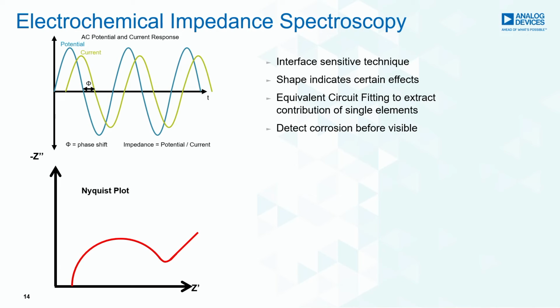This way you can, for example, detect corrosion before it's even visible, check if your coating is working, for example, is it taking up water? Or you can make label-free immunosensors. Label-free means often, for example, if you look for a certain DNA, you have to attach another molecule that will give a nice electrochemical signal. With impedance spectroscopy, the change of the interface due to interaction of certain molecules can be large enough to have a good signal without introducing any labels. All right, there is a bit of a disadvantage. It's a rather complex technique, and you have to invest quite some knowledge to analyze it properly.